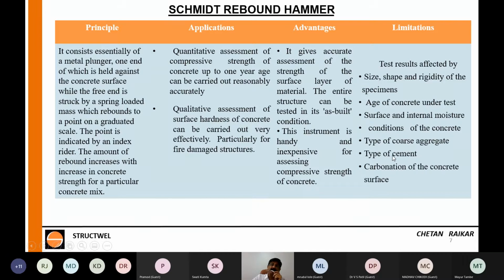See, the Schmidt hammer which you get in the market is calibrated for OPC. But what you get today is a cement which is mixed with fly ash. Even at the manufacturing level, a few percentage of fly ash is added. So it's no more a pure OPC. It is like PPC, or having pozzolanic ingredients in it. So can we directly use the Schmidt hammer even if it is brand new for the concrete on site? Probably no. Or use it with a pinch of salt. So that's where the expertise comes in.